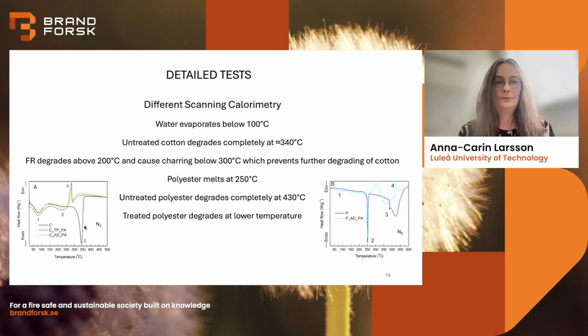That is endothermic when we break down the molecules that make up the cellulose fibers. The same for polyester. Polyester doesn't absorb water, but the flame retarded sample has some water that is released. Here is the melting point of polyester, and here the polyester starts to degrade. We can also see some small exothermic peaks from some char formation.